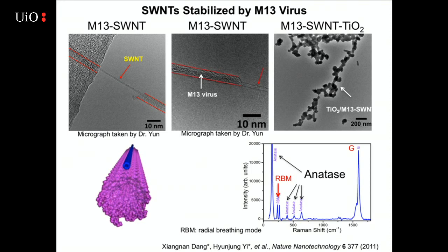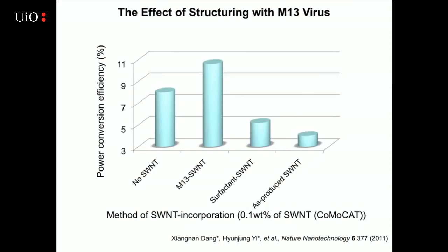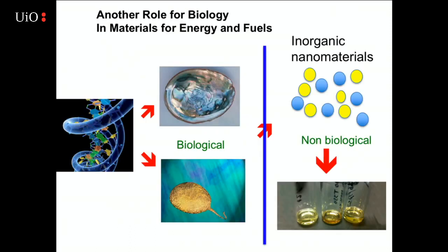And so now what we have is this is a transmission electron micrograph with a virus picking up a single carbon nanotube right there, and then we will grow titania around this structure. And based on doing this, this is with no single-walled carbon nanotube. This is with the M13 single-walled carbon nanotube, just a surfactant, and as produced. And based on this, we're able to get an increase in 33% efficiency of the dye-sensitized solar cells made in our group. And it was 0.1% biology that led to the increase in this solar cell efficiency.